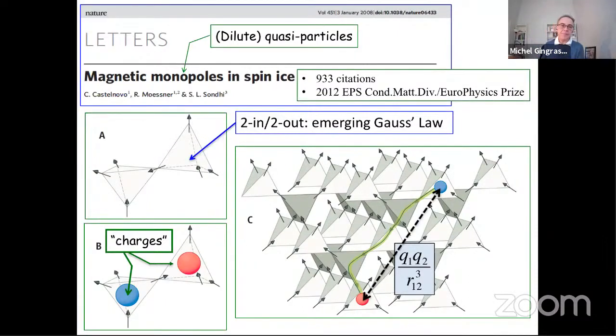And the field theory corresponds to implementing the ice rules by a fictitious, let's say, electric field, where you have charges which are causing this electric field. And so the ice rule corresponds to a situation where, if you imagine that you discretize this emerging field on the pyrochlore sites where the spins are pointing, you can see that this tetrahedron here has two spins pointing in, two spins pointing out. So the lattice calculus, the vector calculus of the field, will tell you that this field is divergence free. There's as much magnetic flux going in the tetrahedron as there is going out.